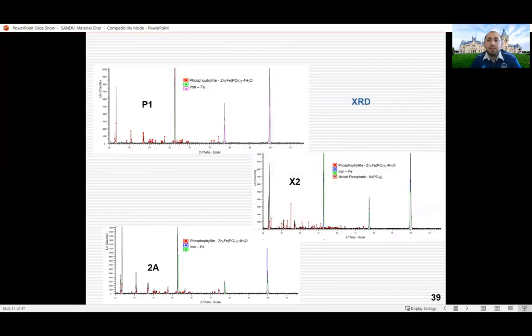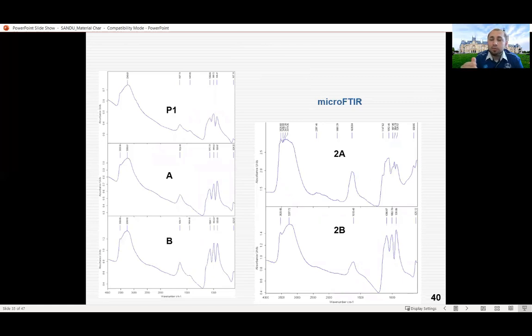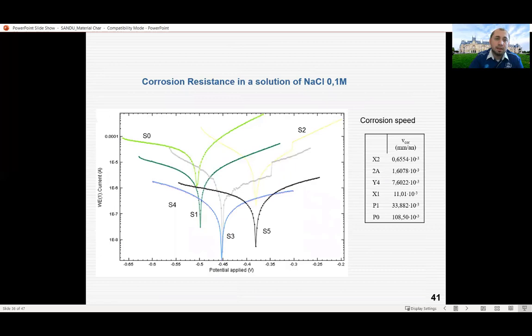Then we go for the XRD samples when we get all the samples in there, and XRD allows us to get the compounds. If the EDX gets us the elements, like iron, zinc, and so on, XRD gets us the compounds. Usually when we get the chemical composition and we get the chemical structure for the phosphate, we have the main ingredient, called phosphophyllite. This is a compound very important when we speak about the corrosion of the phosphate layers. Then we have the micro-IR here, where we also get the spectrums and we identify the compounds. So if we are not sure on XRD what compounds we have there, we can also use the infrared spectrometer to identify the compounds in there.